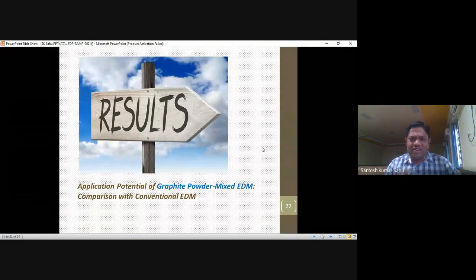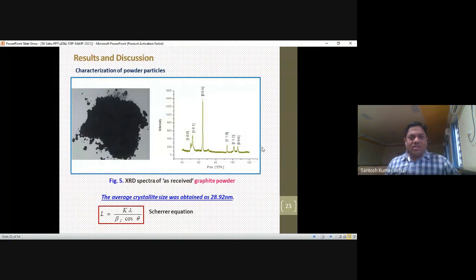Now, in the first result, I will discuss part 1. When you use the graphite powder in EDM, you have to compare it with conventional EDM. First, see what powder we can take from the market. You test the graphite powder by XRD, see the figure, and the average crystal size is calculated as 28.92 nanometer with the help of the Scherrer equation.